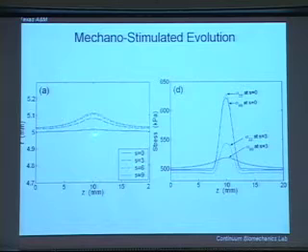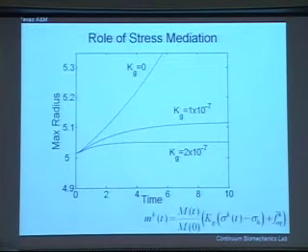So as we allow this vessel to numerically grow, which is by removing the old overly stressed constituents and replacing them with new constituents, this vessel enlarges, and what you see is even in this first time step, this large change in geometry, the stresses come down dramatically. And if I showed you here, you can see it's a curve converging to this geometry. The stress will essentially go back to normal. So we think that this is consistent with a lot of the data that we've seen in flow-induced remodeling, hypertension, et cetera, and indeed is explaining some things we see in aneurysms.